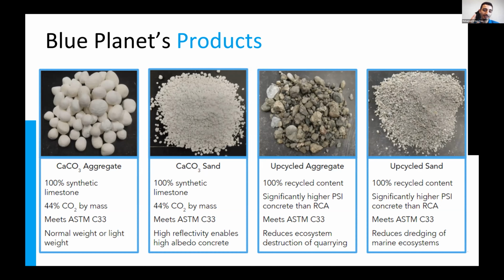An advantage of the calcium carbonate sand, or just calcium carbonate that we're producing in general, is that it has a high reflectance. So when you replace enough of the sand in the concrete with our calcium carbonate sand, you have a chance to increase the reflectivity of the surface of the concrete. So not only are we focused on the CO2, but this also impacts the albedo of the concrete and really fights the heat island effect.